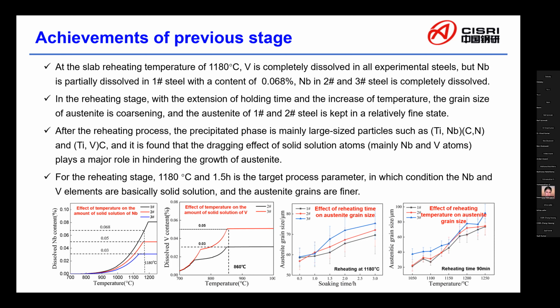In the reheating stage, with the extension of holding time and the increase of temperature, the grain size of austenite is coarsening, and the austenite of number 1 and number 2 steel is kept in a relatively fine state. After the reheating process, the precipitated phase is many large-sized particles, and the dragging effect of solid solution atoms plays a major role in hindering the growth of austenite.